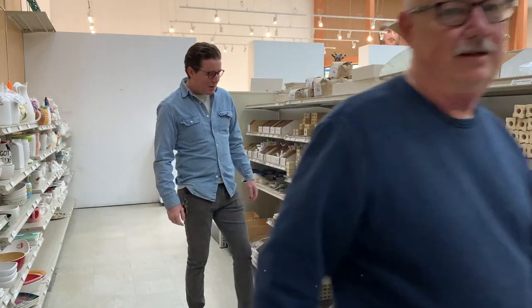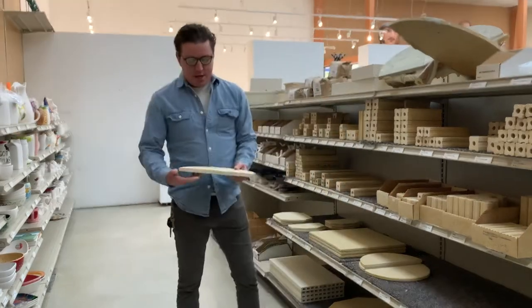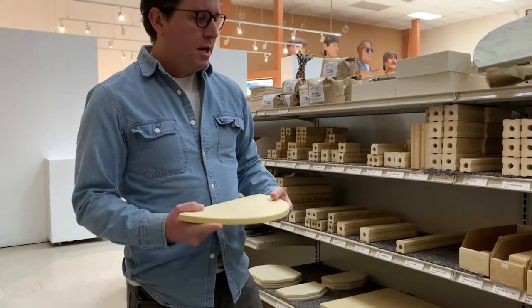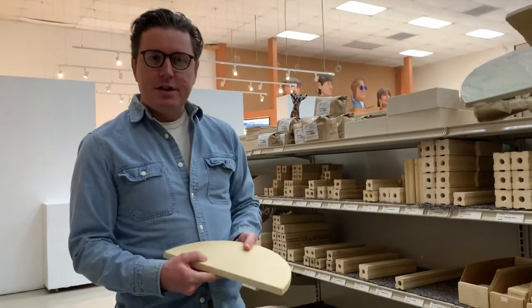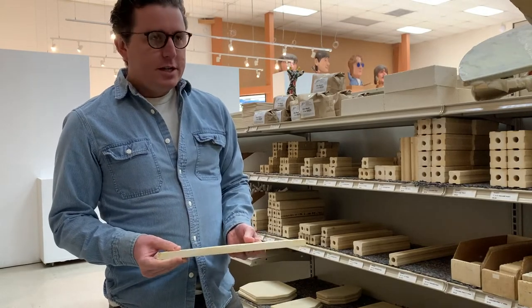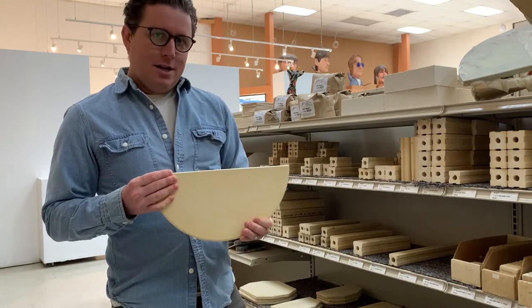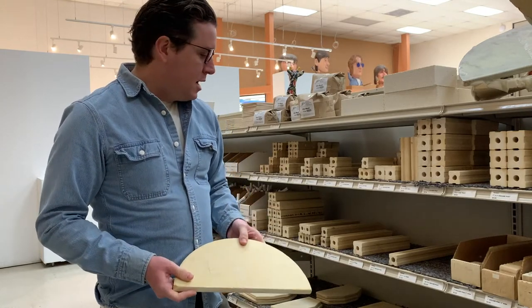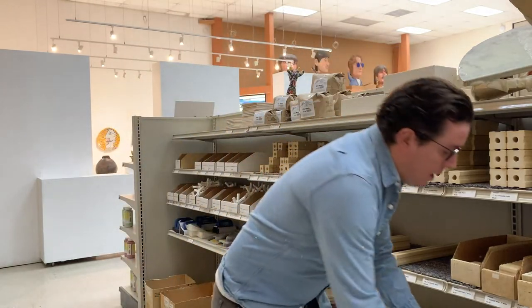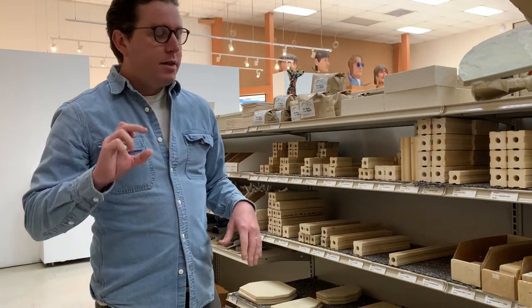These are our kiln shelves here. These are all a cordierite material — it's a clay refractory composition. They sell these shelves at different thicknesses for different temperatures. This is the 5/8-inch thickness, which is ideal for the lower temperatures in ceramics. We also sell one-inch versions, which are more ideal for the higher temperatures — cone 5 and up, you're going to want a thicker kiln shelf.